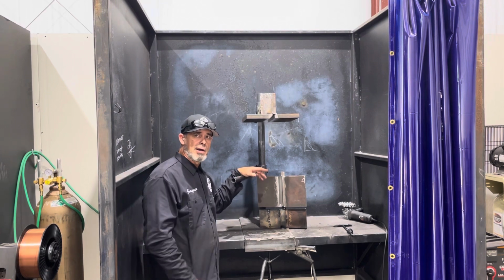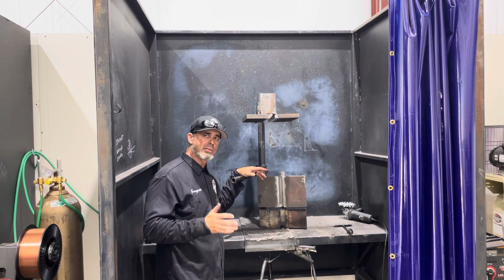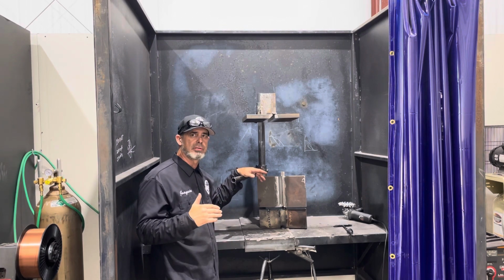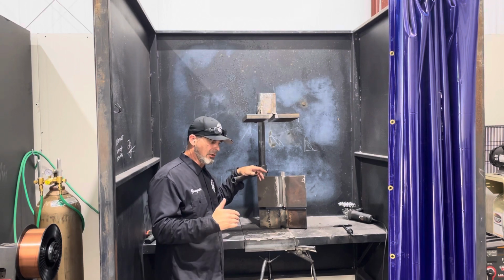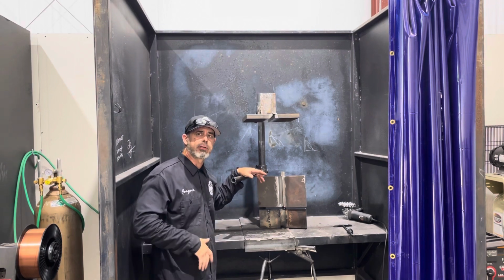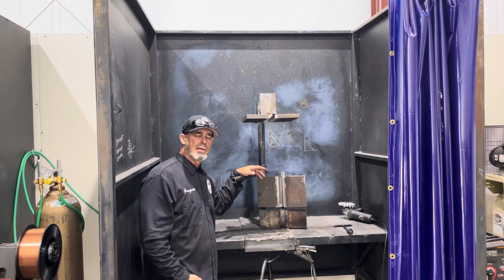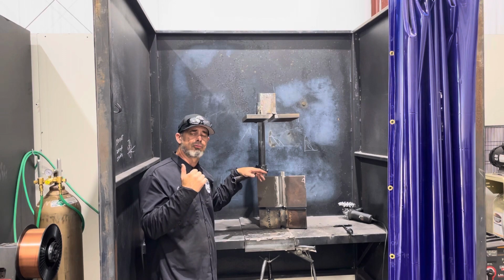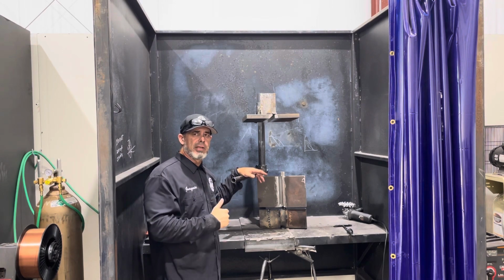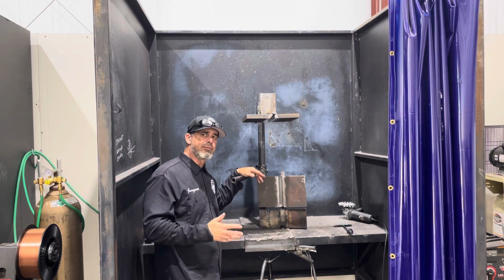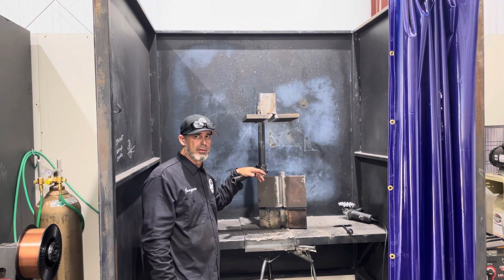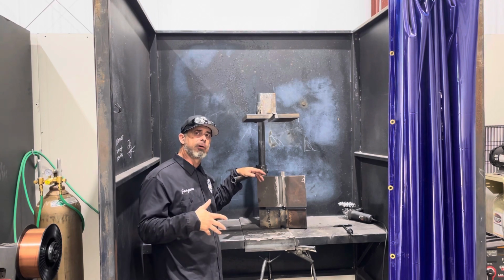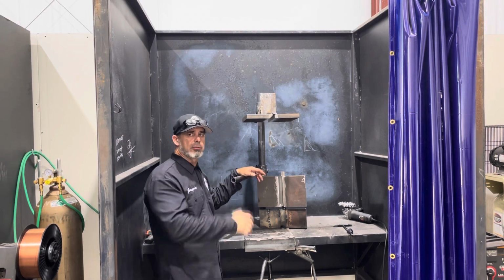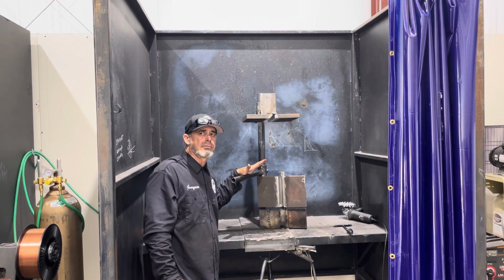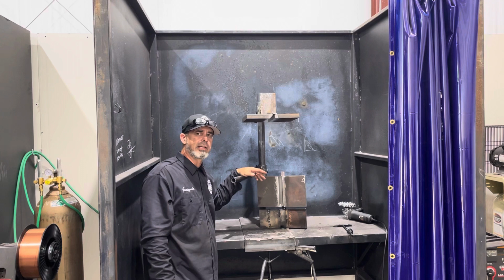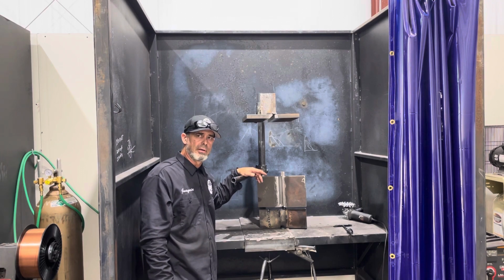Remember, I'm going to drag. My parameters for the voltage on the welding specification, it says a minimum of 25 volts. All right, minimum 25 volts. So I'm going to start at 25 volts. I actually had a test piece and I did some stringers on it at 25 volts with different wire speeds. My wire speed for my overhead was really solid at 200 inches per minute. And on my vertical, between 150 and 175 looked better than 200. So it was a little bit slower on my wire speed on my vertical and a little bit faster on my overhead. Now, you're welcome to flip-flop, or stick to one speed and work with it. It's up to you and how comfortable you are. Let's get to it.